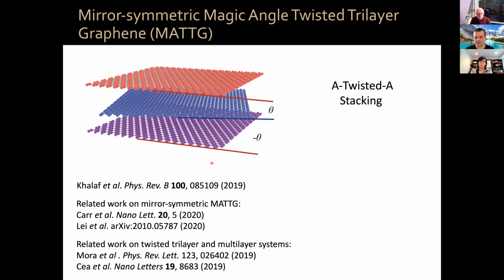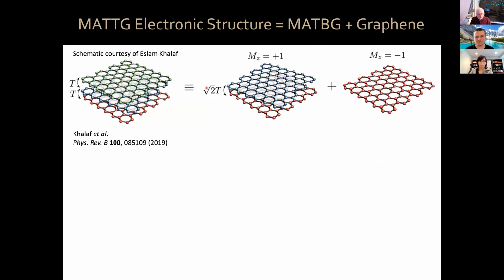Now, this structure is quite interesting because essentially you have these 3 layers which are coupled with a tunneling element T between each layer. The tunneling strength between consecutive layers is T, and it turns out you have a 3x3 Hamiltonian where you can do a basis transformation such that the Hamiltonian becomes block diagonal. One block is a magic angle twisted bilayer graphene-like block, but with a tunneling element square root of 2 times T. And the other block is a 1x1 just monolayer graphene block.